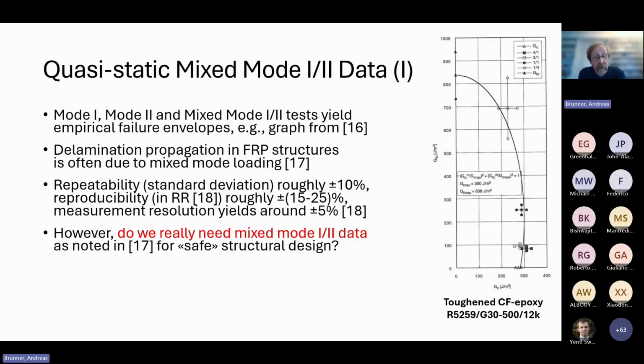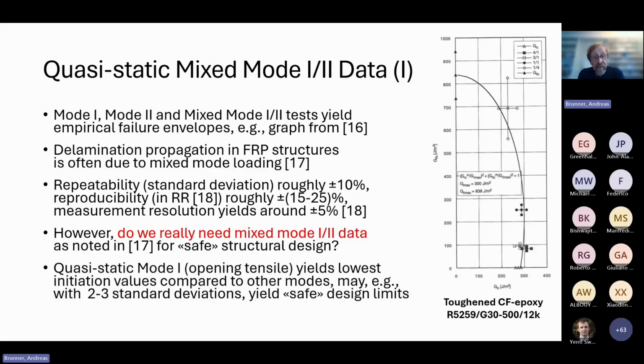Now, the question I really want to raise is, do we really need the mixed mode 1-2 data for safe structural design? If you look at the graph, you start at the value for mode 1 at around 300 or slightly below, and then this failure envelope goes up quite steeply. So in principle, this could suggest that if you simply take the mode 1 and apply sufficient safety factor, then you could probably do with that, and you wouldn't need any mixed mode test for the design. Of course, the question then is, what would be the safe design limit in terms of the standard deviation?